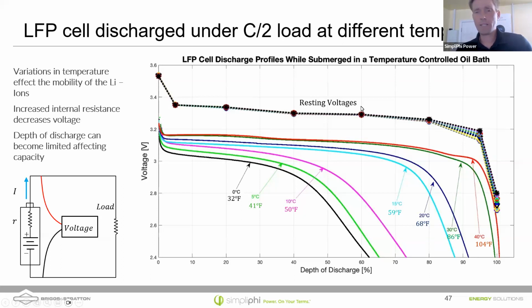Then what I'm showing is I had the students hold the cells at constant temperatures in oil baths and run discharge cycles all at C/2. So a fairly fast discharge cycle, but you can see how much the graphs shift down. The colder you are, the more of a downward shift you'll have for the curves. The good thing to note is in cold environments, as you discharge a battery, it won't stay at the same temperature. It'll rapidly heat up.